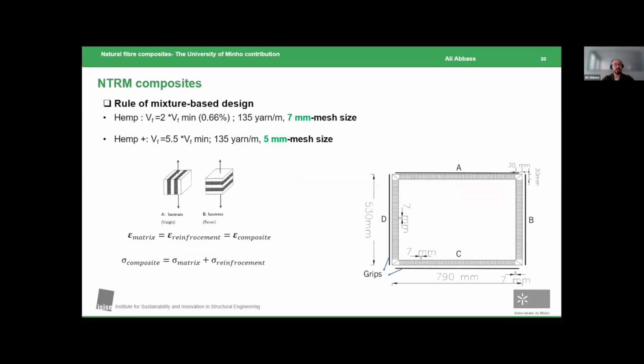So now let's move to the composite materials. We designed the composite materials based on an isostrain model, using the rule of mixtures to evaluate the critical fiber volume fraction. We used two fiber volume fractions. The first one is double the critical fraction, and the second one is 5.5, resulting in 7 millimeters and 5 millimeters mesh size.